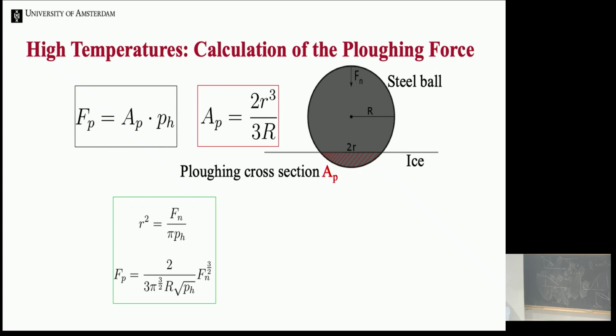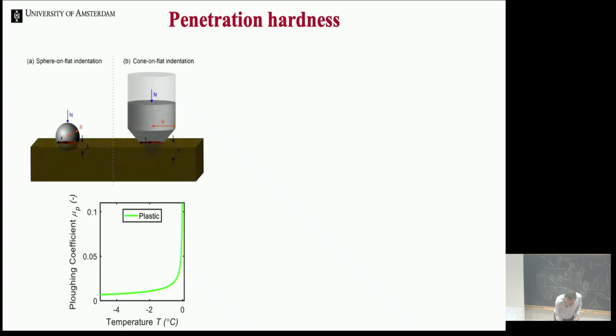And this area I can, of course, transform into a contact radius, and there's the radius of the sphere. The normal force is the contact area times the plastic deformation limit, the penetration hardness of the ice. So that is an easy calculation. We can measure the penetration hardness.